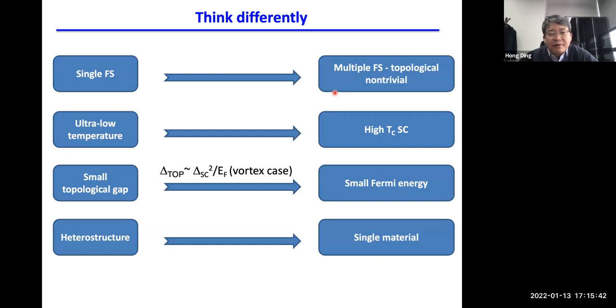So from the single Fermi surface, we have to think about multiple Fermi surfaces, multiple bands, and part of this has become topologically non-trivial. To overcome the ultra low temperature problem, we need to think about high TC superconductors. And to obtain a large topological gap, which in the vortex case is essentially proportional to the superconducting gap squared divided by EF, the Fermi energy. So if we can increase the superconducting gap and also significantly decrease the EF, then we can get a relatively large separation between the zero mode and the other non-zero modes in the vortex. So we need a small Fermi energy.